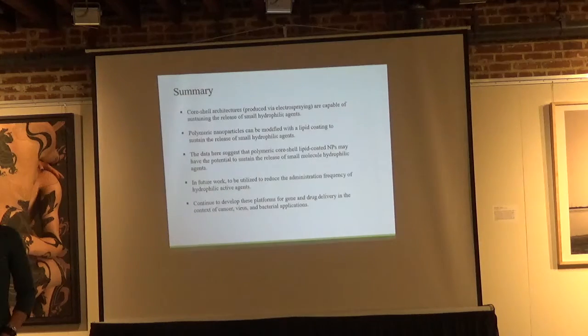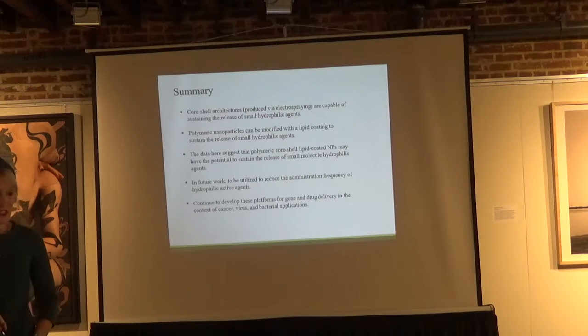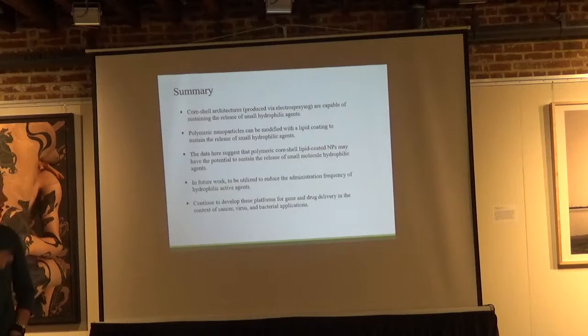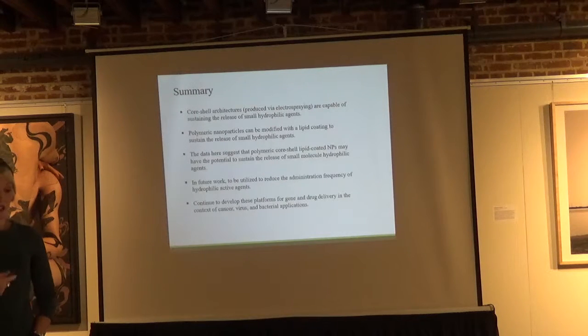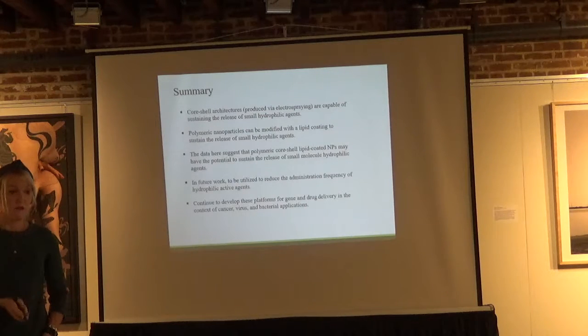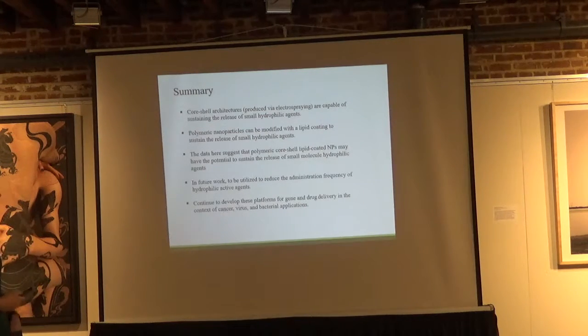And so yeah, in summary, core-shell architectures produced via electrospraying are capable of sustaining the release of hydrophilic agents. Polymer nanoparticles, you can modify these with a lipid coating, and while we've done this with our emulsion-based formulations, we still need to move this forward to do that with our electrosprayed formulations. Our data here suggests that polymeric core-shell lipid-coated particles, or just polymeric core-shell particles, have the potential to really do a great job in sustaining the release of rhodamine B. That's no easy feat. And in future work, we'd like to utilize this to either reduce administration frequency of hydrophilic agents or just extend the delivery through which we can deliver these hydrophilic agents alone.